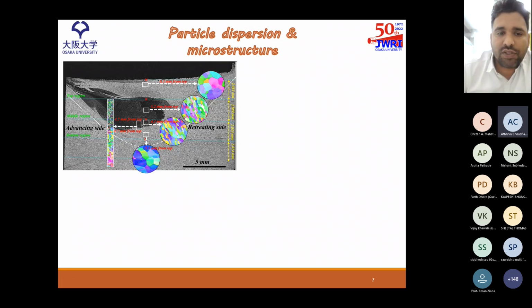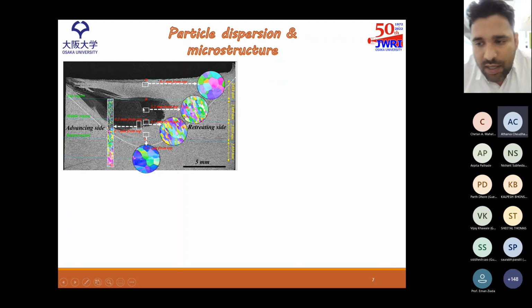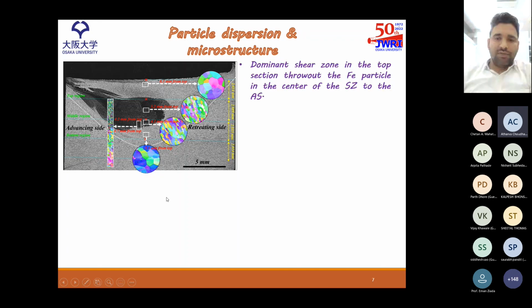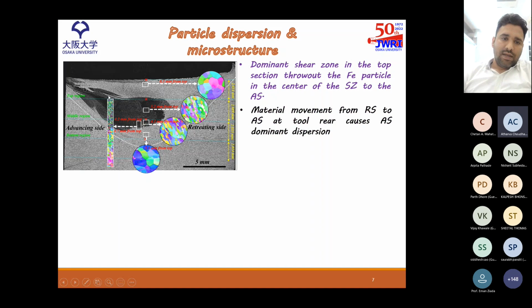Now coming to the particle dispersion microstructure, this is the cross-section micrograph. So this black part can be identified as the iron-rich zone, and this is a fully etched micrograph. So a very well stir zone and other zones can be classified. Now the two interesting features observed from here are that this is the advancing side and this is the retreating side. So the particles are mostly dispersed on the advancing side instead of the retreating side.